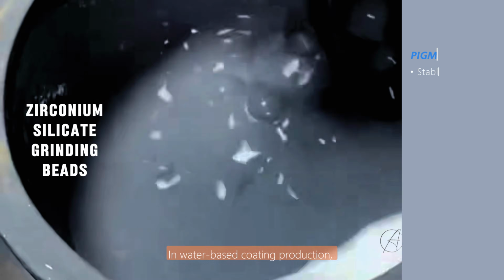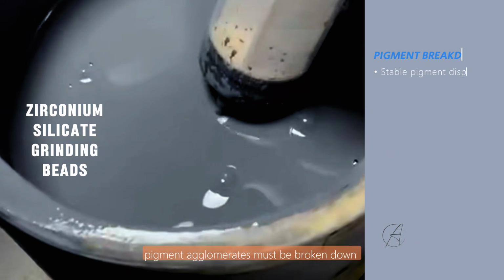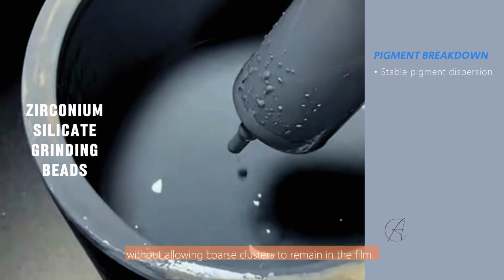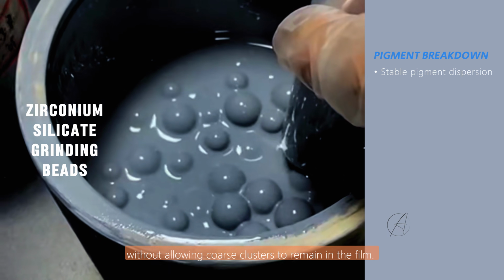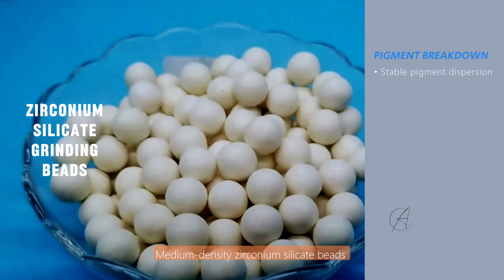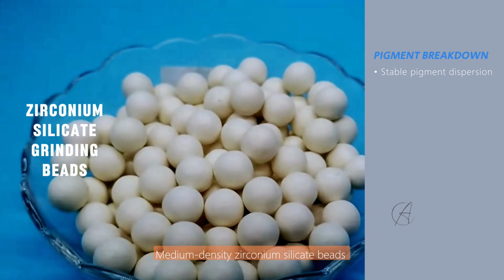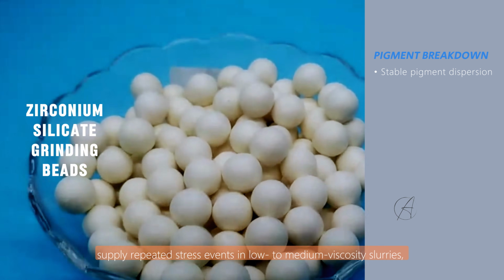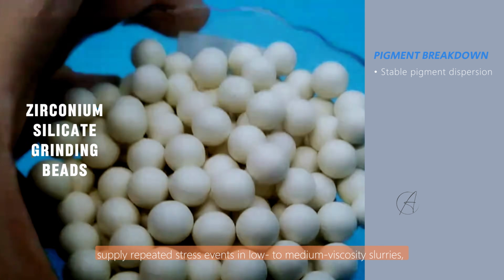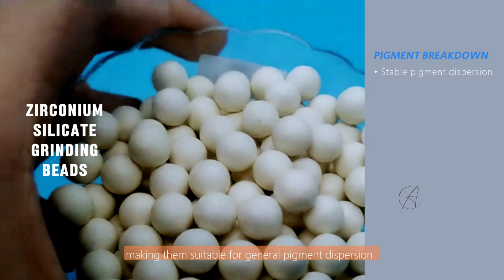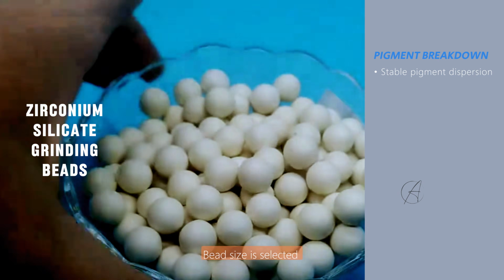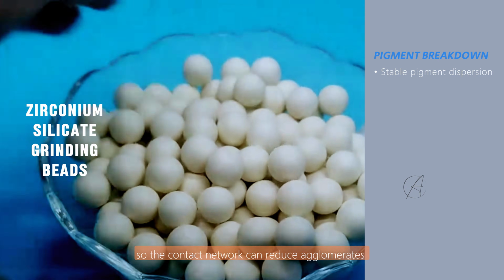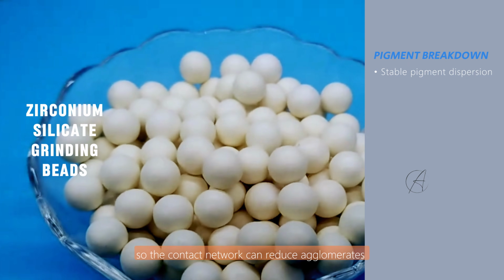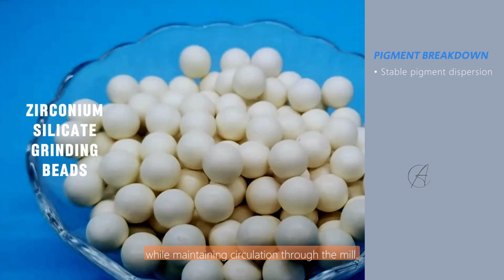In water-based coating production, pigment agglomerates must be broken down without allowing coarse clusters to remain in the film. Medium-density zirconium silicate beads supply repeated stress events in low to medium viscosity slurries, making them suitable for general pigment dispersion. Bead size is selected so the contact network can reduce agglomerates while maintaining circulation through the mill.